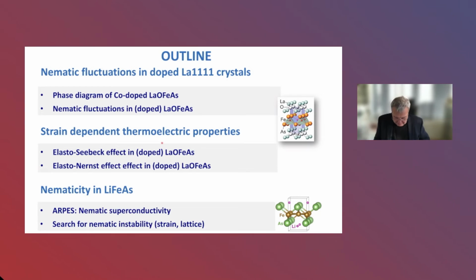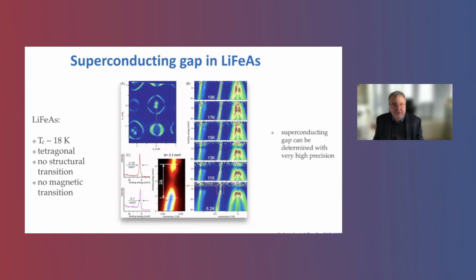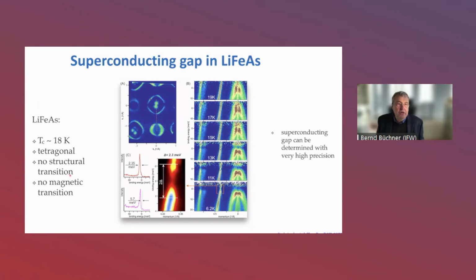I will take the remaining time, I still have a couple of minutes, to switch gears to a completely different compound, and this will make clear that these iron-based superconductors are very, very different in their respective properties. This lithium iron arsenide is very different. The parent compound is already a superconductor. There is no structural phase transition, so no evidence for long-range nematic order, no evidence for long-range orbital order. There is no magnetic transition found so far in these systems. And still it's a nice superconductor.